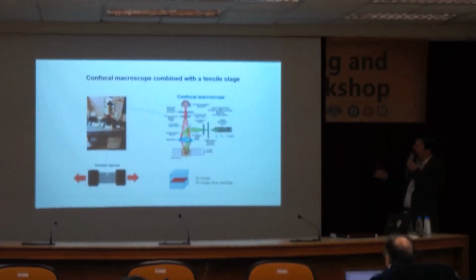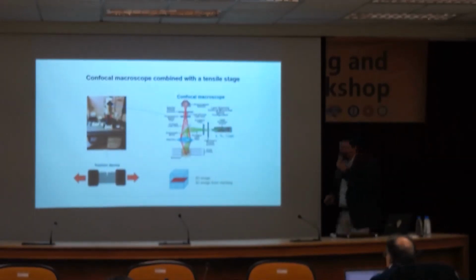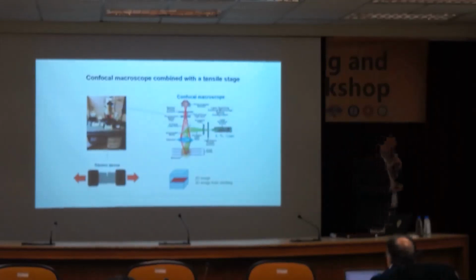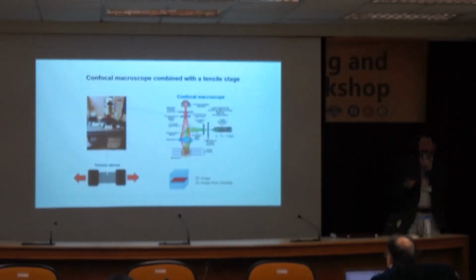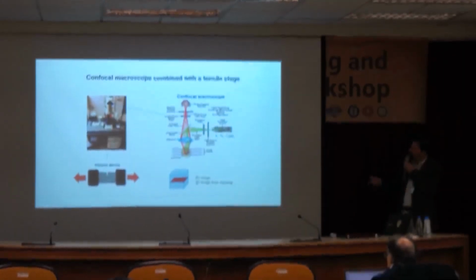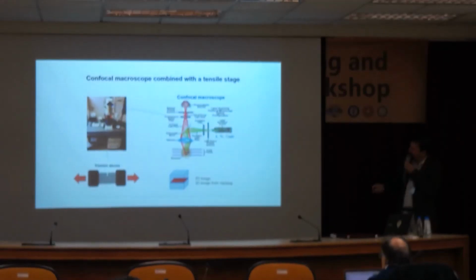So instead of using a microscope where it's typically in inverted configuration, we use a low magnification confocal setup, which was actually developed for biologists who wanted to look at fetus and larger objects. But we can also look at a crack, so we can put a tensile device underneath the confocal macroscope and then illuminate it and do a 3D image of the crack tip.